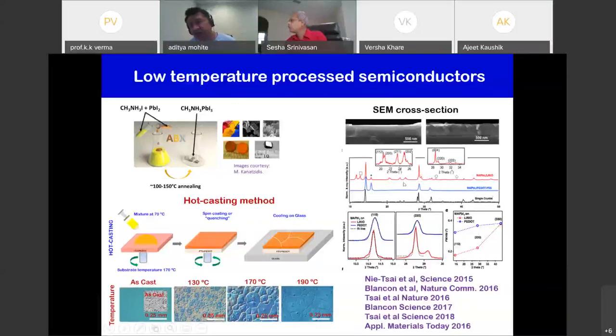At least to me, this was remarkable: this is the first time you had a solution process material and you could simply spin coat it and get a material that had these sharp diffraction peaks, which are observed in single crystals. That I thought was sort of amazing. And so we did a lot of work in understanding this process.